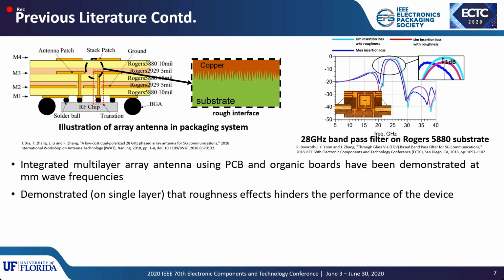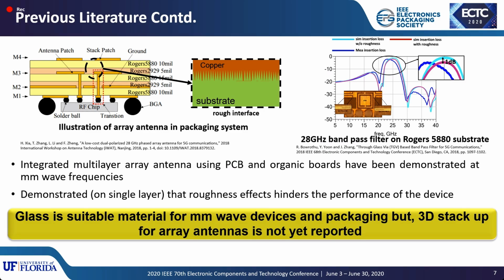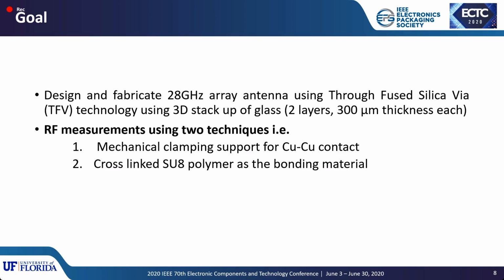But we can also see that multi-layer array antenna structures are usually demonstrated on PCB or organic boards, which suffer from very high roughness values. So, glass is a suitable material for millimeter wave devices and packaging, but 3D stack-up of glass for array antennas is not yet reported. So the goal of this work is to design and fabricate a 28 GHz array antenna using through-fused silica via technology, where we stack up two glass layers, with the thickness of each layer close to 300 micron. The RF measurements are performed using two techniques. The first is mechanical clamping support for copper-to-copper contact, and the second method is using cross-linked SU8 polymer as a bonding material between both substrates.